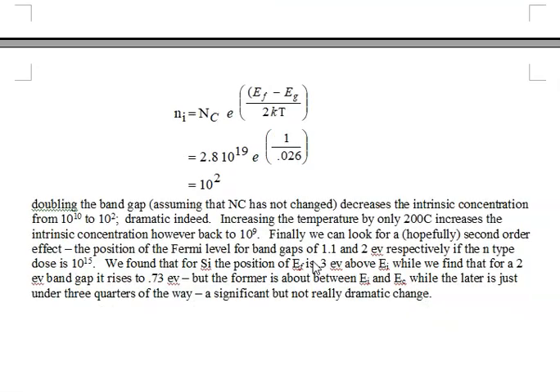But here, this really changes, and it changes a lot because instead of having a 0.56, here we have a 1, and that's a big deal. So from 10 to the 10th to 10 squared. And I didn't actually perform the calculation here in detail, but if we increase the temperature again by only 200 degrees Celsius, the intrinsic concentration will increase from 10 to the 10th back to 10 to the 9th, almost canceling out the increase in band gap.